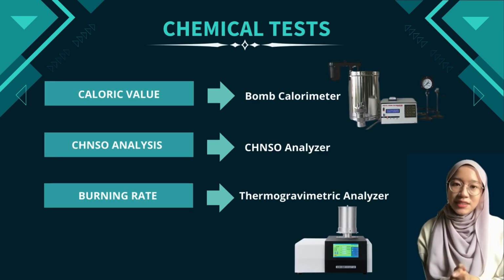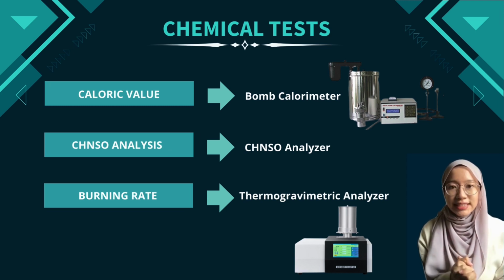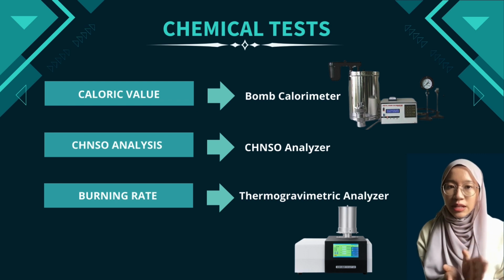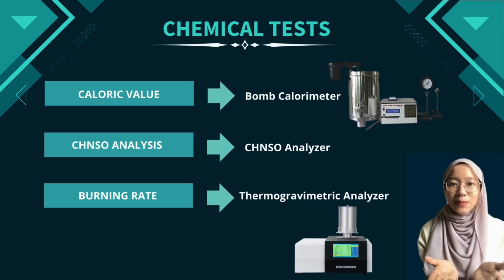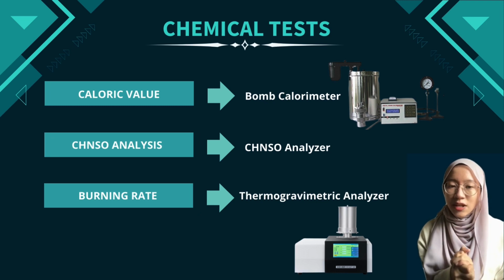For chemical tests, several tests will be conducted for determining the caloric value, proximate and ultimate analysis of the produced samples. The caloric value is measured following the ASTM D2015-96 standard using the bomb calorimeter. Another analysis was conducted following the guidelines of ASTM D5373-02 using the CHNSO analyzer to determine the elemental composition of the samples. TGA is used to analyze the combustion characteristics of the samples.